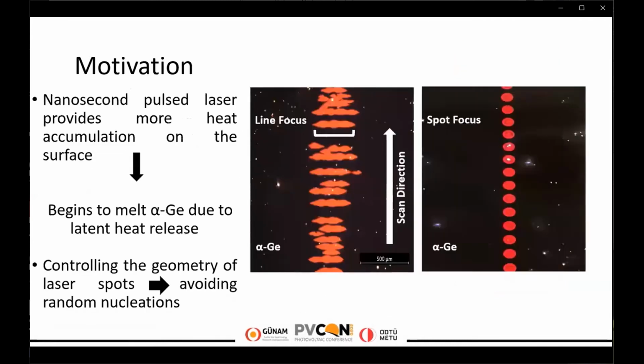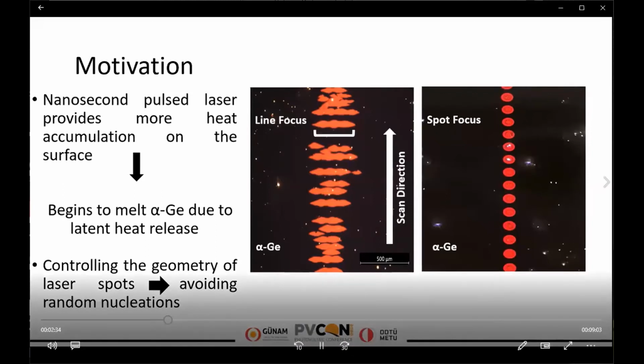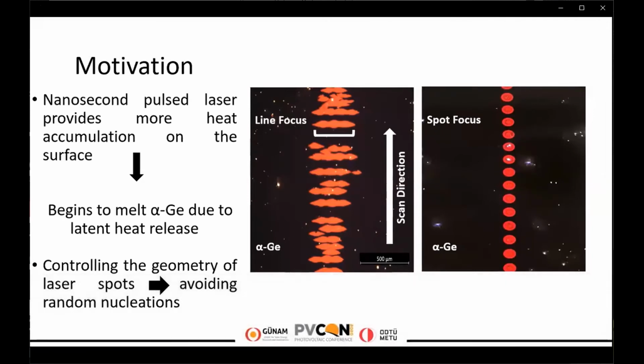Nanosecond pulse laser provides more heat accumulation on the surface, and the crystalline grain domains were aligned by sustaining heat accumulation over the film. Controllable geometry of laser spots delivers the benefit of avoiding random nucleation, so that intended crystalline structures can be projected over the film. Unlike spot focus scanning, the size of individual polycrystalline germanium domains can be increased by line focus scanning.